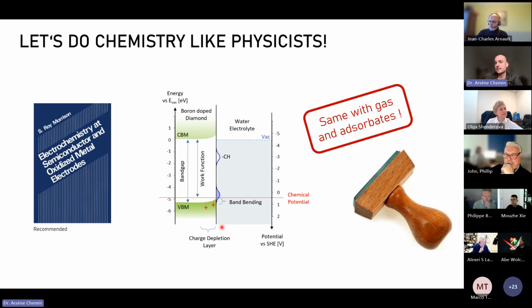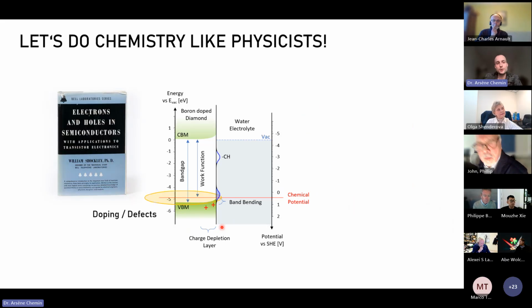By the way, that also works for adsorbates. So if you're working in air, for instance, and you're probing some sample with a diamond probe, you will have the same kind of charge transfer between the adsorbed molecule and the diamond. And this framework is actually very useful because we can really understand a lot from it. So on the diamond side, the Fermi level, for instance, will be completely dominated by the different doping and defects. So depending on if you're working with boron doped diamond, nitrogen doped diamond, or just pure diamond with defects, you can see some variation of the Fermi level.